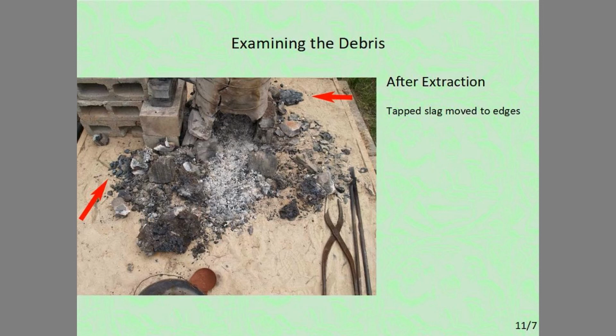Of interest to any archaeologist watching this presentation will be the remains left after extraction itself. The first thing you see is that tap slag has been moved away from the furnace after it's been created, mainly to get it out of the working area. During extraction, hot debris can be expected to be pulled to either side for the safety of the workers. One of the first materials to be removed is the charcoal fines packing from underneath the slag bowl.